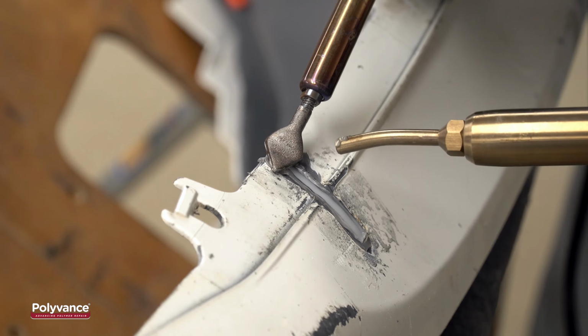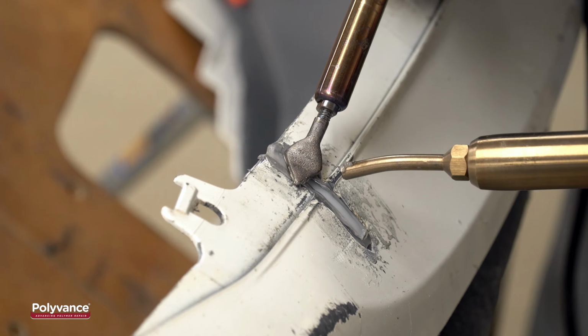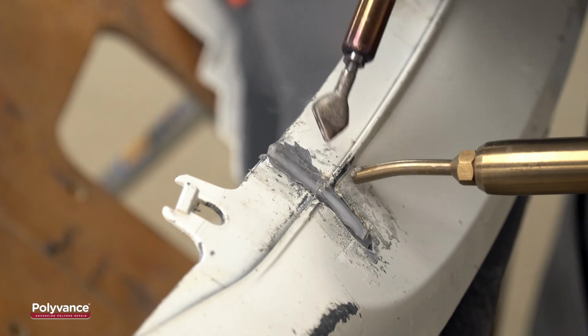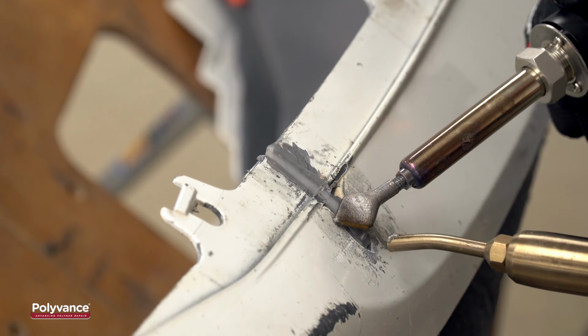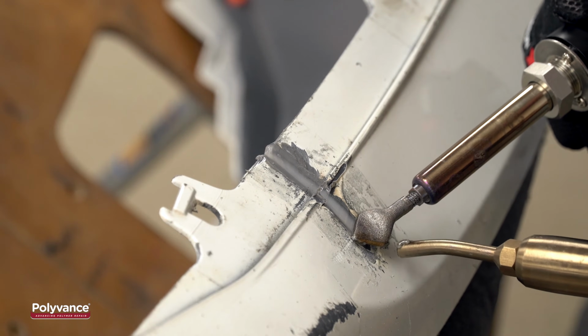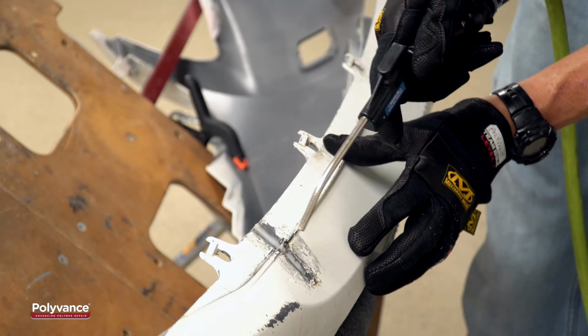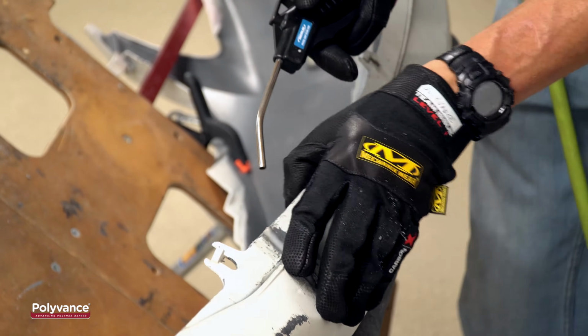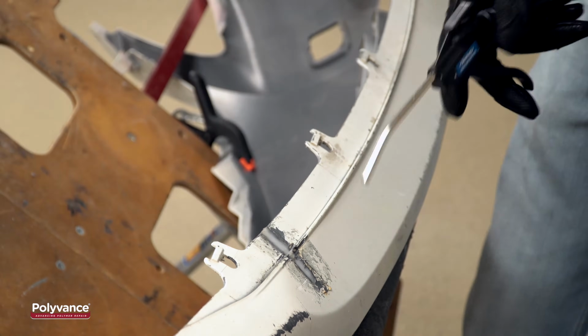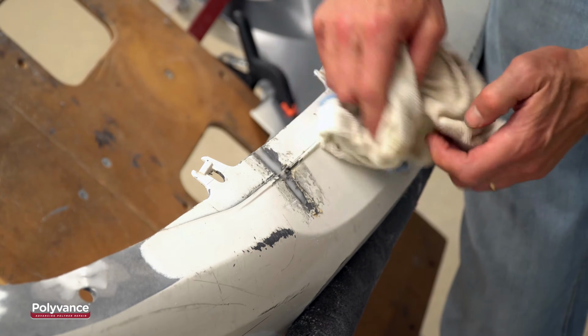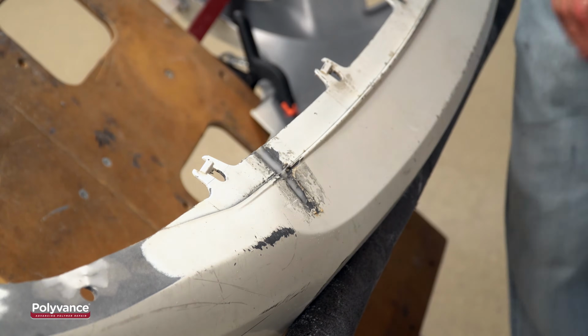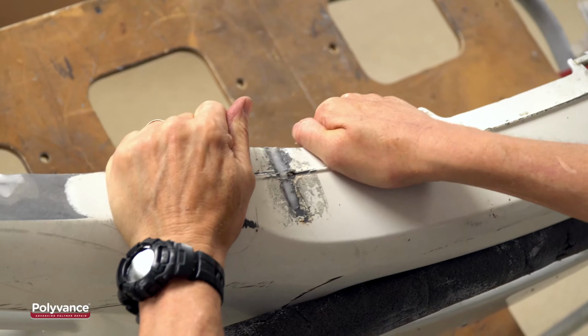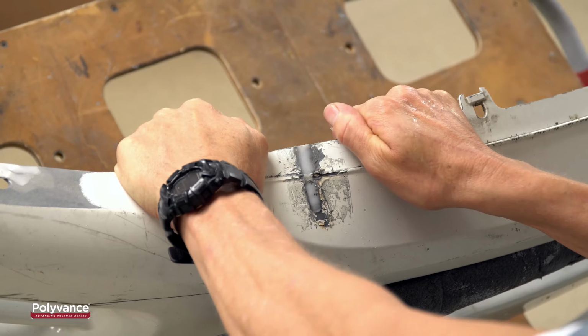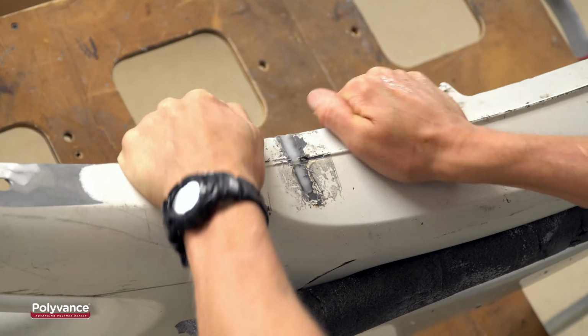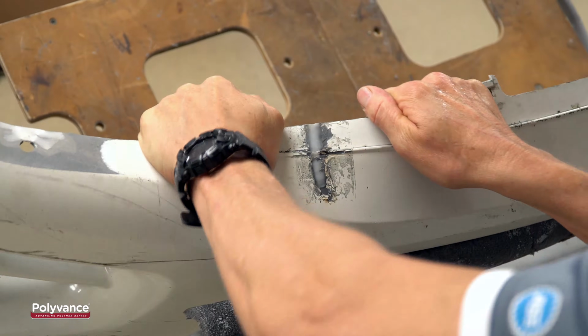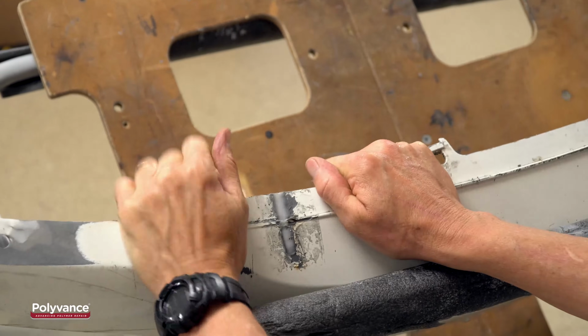When that is done, use the airless welder to smooth the top of the weld. Lay the welder on the surface and preheat the welding rod with the nitrogen at the same time. Let the weld cool to room temperature before sanding or testing its strength. This can be accelerated by blowing it with compressed air or applying cold water. Test the strength of your weld before you invest any time in the refinishing process. As you can see, this weld will be more than sufficient to carry this bumper to its next accident.